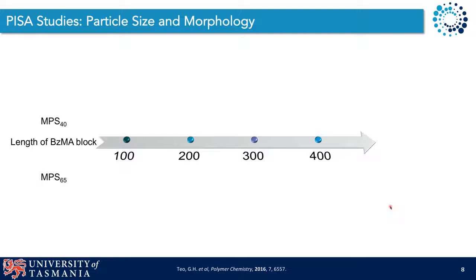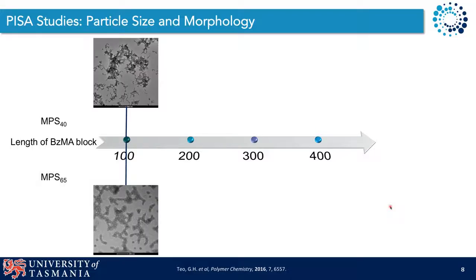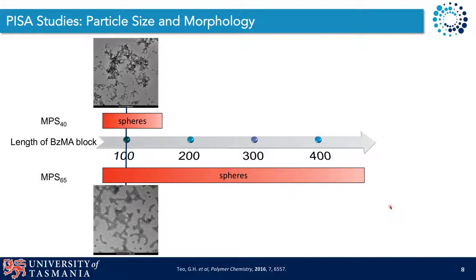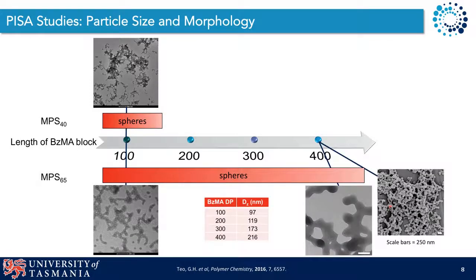We then went on to look at how the length of the benzyl methacrylate block influences both the size and morphology of our resultant particles. If the length of the benzyl methacrylate block was quite short, 100 units, we would of course form spheres, being the first self-assembled structure that does form. With our longer stabilising block, MPS 65, we exclusively form spheres across a wide range of DPs for the second block. We could of course tune the size of our spheres from approximately 100 to over 200 nanometers Z average diameter. But this is typical of long stabilising blocks that essentially prevent the fusion and rearrangement of our self-assembled structures.